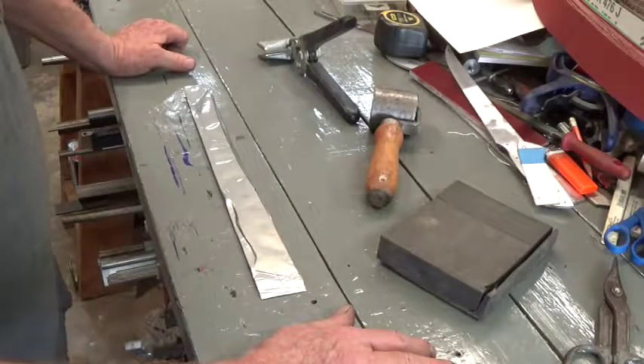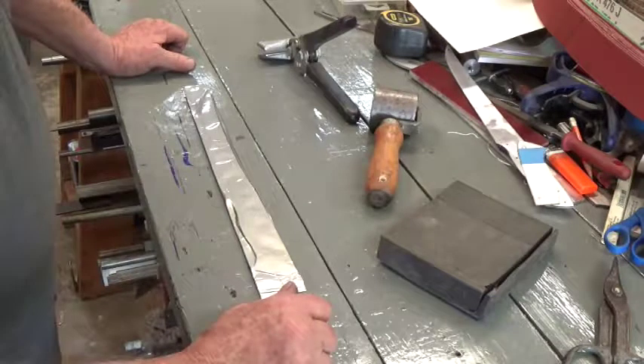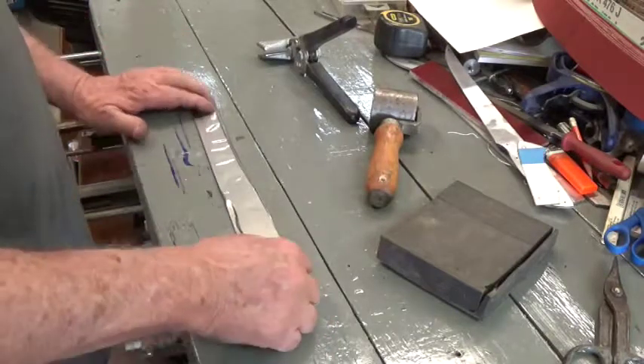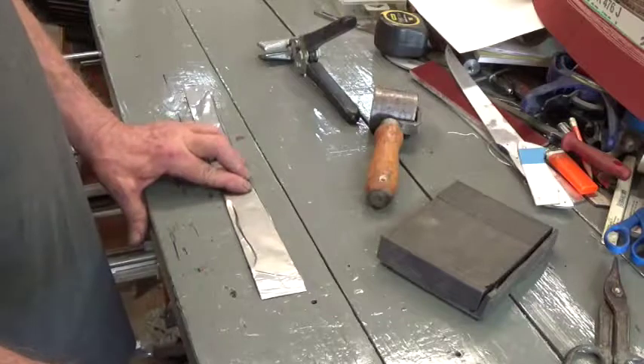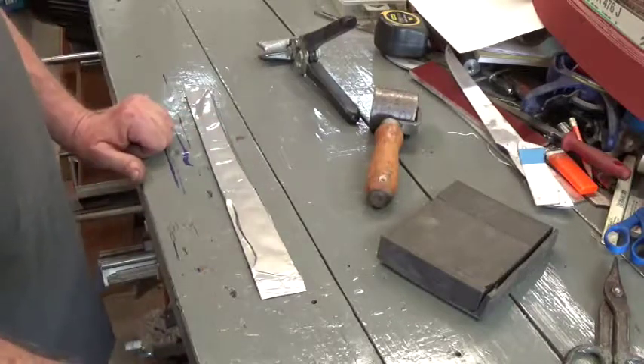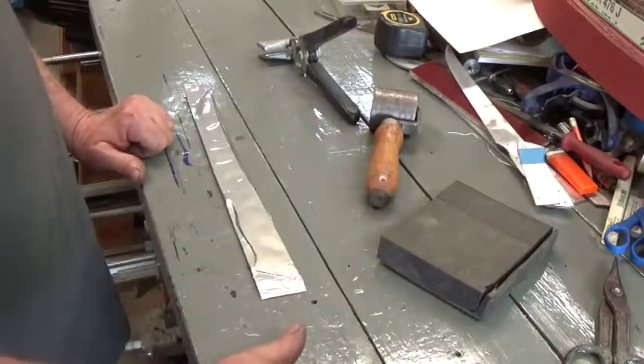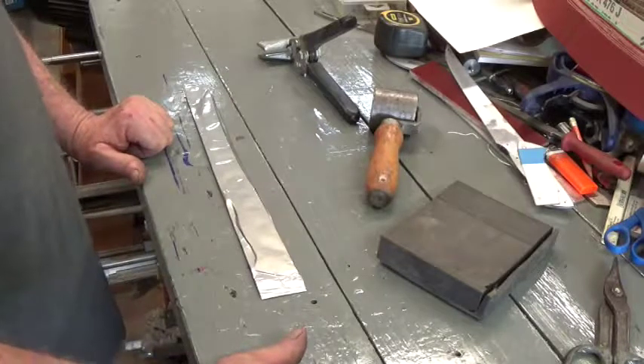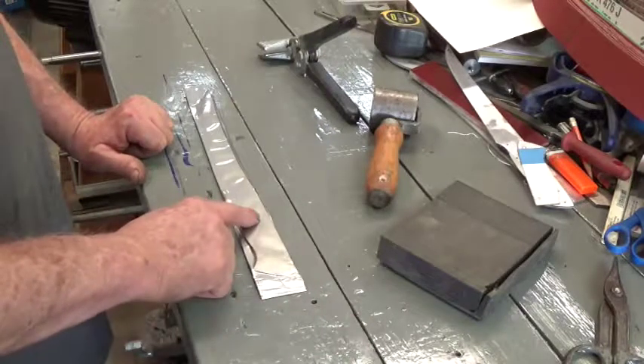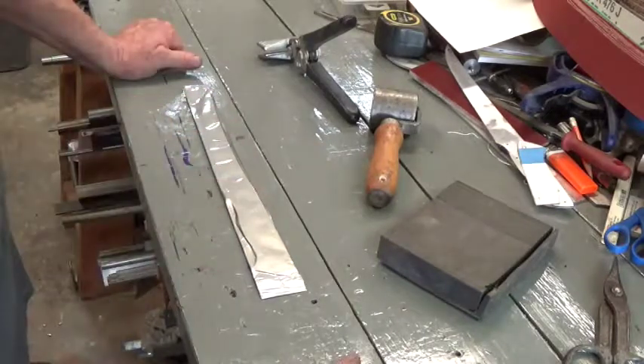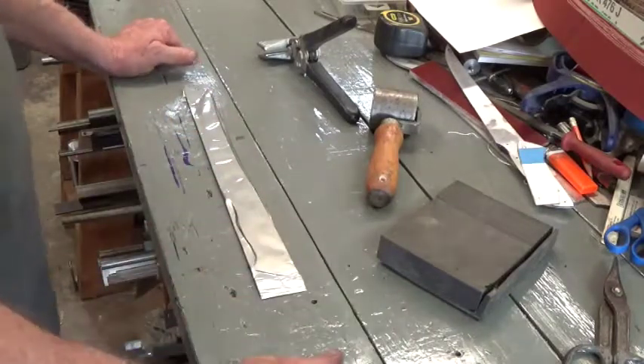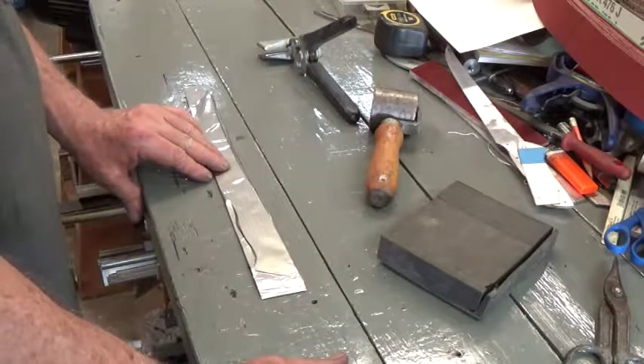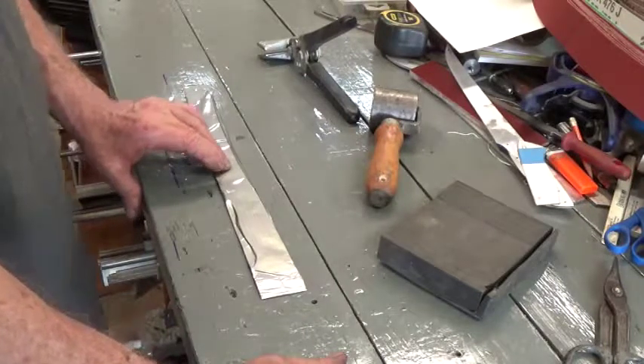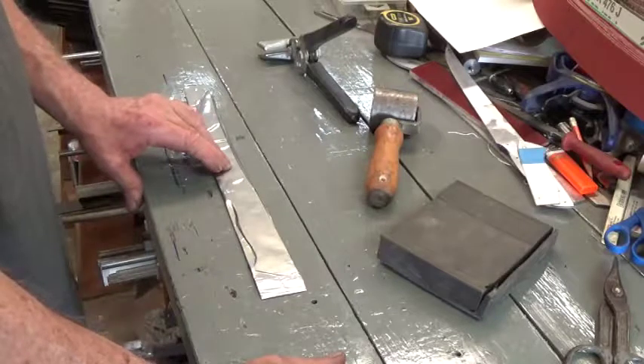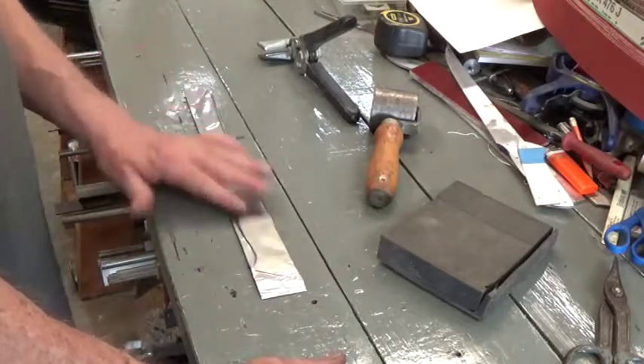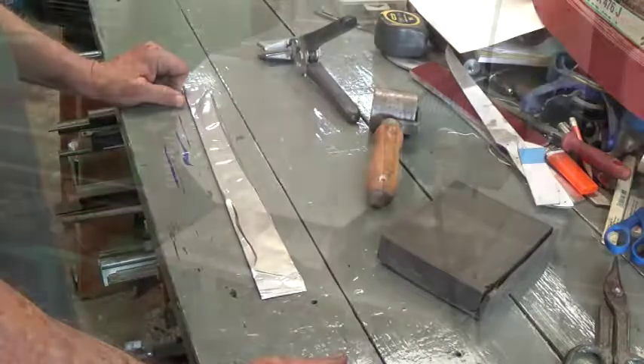And that's followed by 2 draws with this steel. What Crucible recommends, to maintain the corrosion resistance of this grade of steel, is that the lower you can draw it, the lower the temperature, the better off you're going to be. So I'm going with a 400 degree draw for 2 hours, and then when they come down to where you can actually touch them, this goes back into the drawing oven for another 2 hour session at 400 degrees, and then we're done. Then we can clean it up and proceed with the finishing.